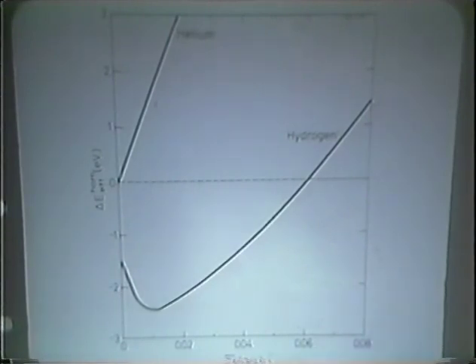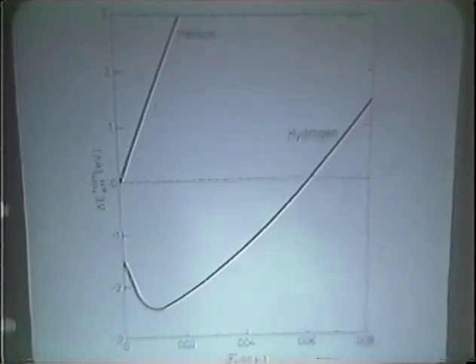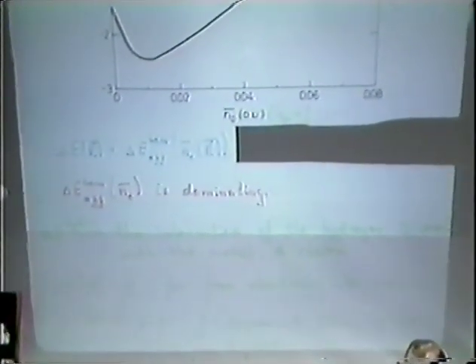You'll see as I go on, you can understand many things that go on in hydrogen-metal systems just from this curve here. Let me point out that the second term there, the hybridization term, which was the interaction with the metal d band, is proportional to 1 minus f, where f is the degree of filling of the d band, meaning that for copper, which has a full d band, it's essentially 0, and then it increases to the left in the transition metal series.